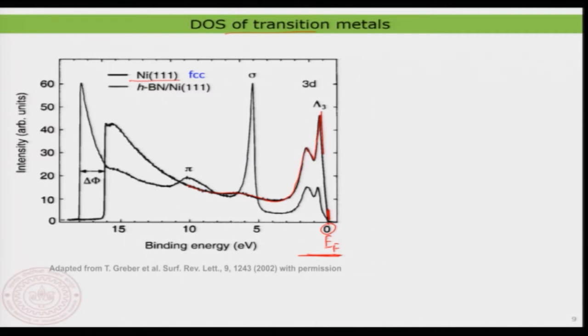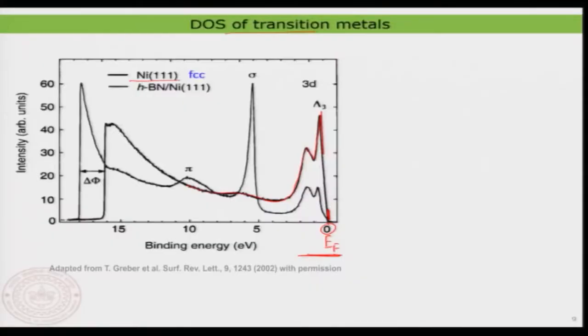So now you clearly see that nickel has a spiky density of state, which is due to its chemical nature itself, and that is an indicator that this nickel is going to be much more reactive than a gold 111 surface, for example. You have already seen that there is no spiky density of state near the Fermi energy in gold. So for most catalytic materials, the density of state near the Fermi energy is much more corrugated than a flat density like in the gold 111 case, or in general gold. That is why understanding the electronic structure of the valence band is quite important for understanding the material property itself, and that is what the application of UPS in general is about.